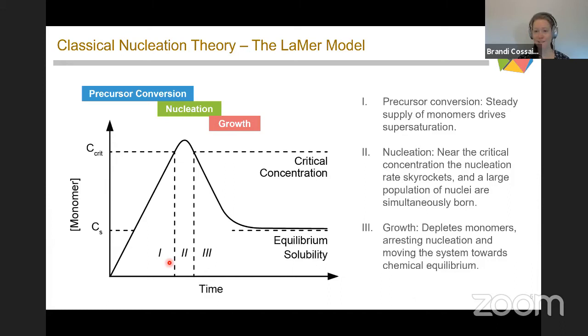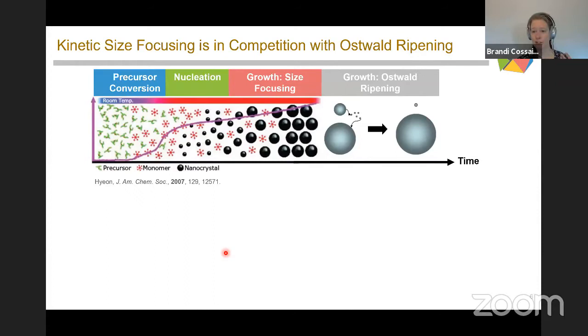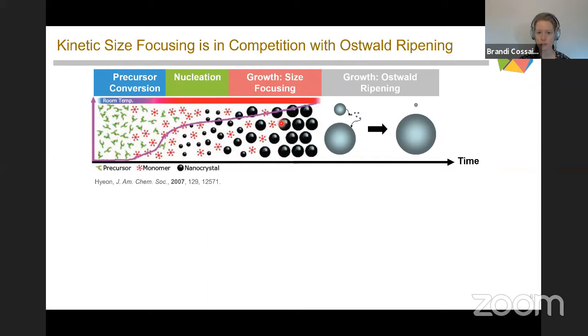Many experiments have qualitatively confirmed this behavior and identified the separate nucleation and growth stages defined by the LaMer-type model. Looking at this in another picture: precursor conversion, molecules converting to small nuclei, nucleation happening quickly - and I've separated growth into two steps. In the first step we undergo size focusing, and then in a later time period, so-called Ostwald ripening.